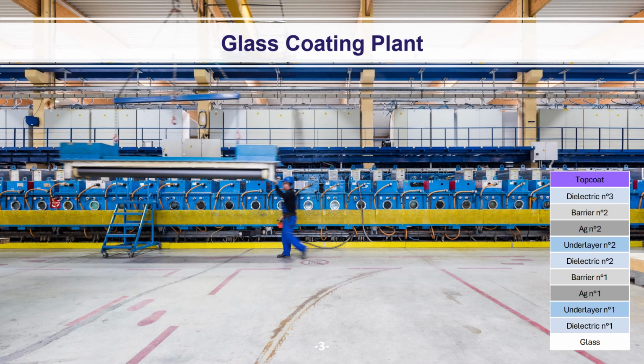This photo shows you a magnetron sputtering system that is performing the coating process. The magnetron sputtering is a vacuum process, so you can see here a large vacuum vessel, and the glass sheets are conveyed in a horizontal position through this vessel while the coating is sputtered on the glass surface in a top-down process. The coating layers that are applied are only a few hundreds of nanometers thick, and the coating is a multi-stack with different layers of metals, for example silver, and dielectric materials, for example zinc tin oxide and silicon nitride, to make an optical filter, transmitting in the visible range and reflective in the infrared.